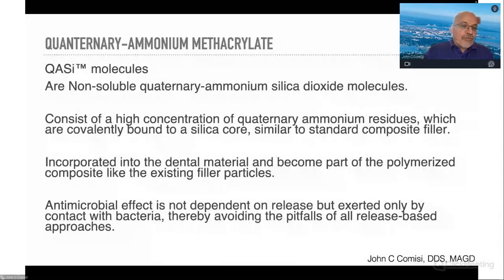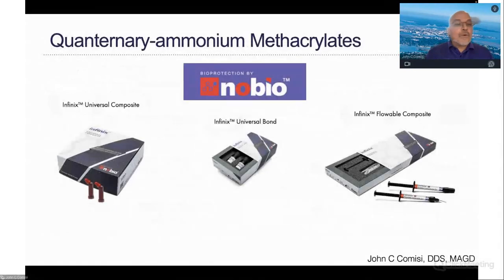One of the possible developments was this QASi molecule, which are non-soluble quaternary ammonium silica dioxide molecules, which have a high concentration of the residue from the quaternary ammonium, which is covalently bonded to a silica core, similar to a standard composite filler. That's great. And it's incorporated into the materials to become part of the polymerized composite, as we do with our existing filler particles in our composites. And according to the information provided, the antibacterial effect is not dependent on release, but instead on contact with the bacteria, which is what Cliff was talking about in the sealant material that he created with the K18. And of course, it's been commercialized by Nobio into a composite, a universal bond, and a flowable composite that is currently available.